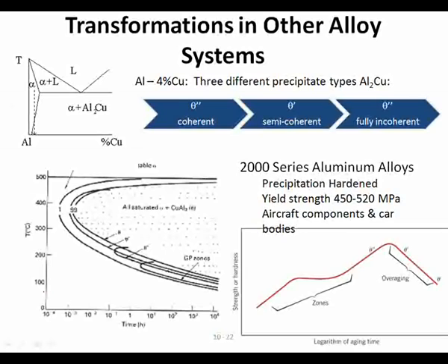And so you have to be careful about that. I mean, aluminum alloy is not our first choice for high temperature applications. But if you're counting on the strength of an aluminum alloy, it's strong because of precipitation hardening. And you need to know that if you're going to be using it at high temperatures, you might lose that strength. Because what happens when we get fewer big precipitates instead of lots of little ones? What happens to our strength? Goes down.